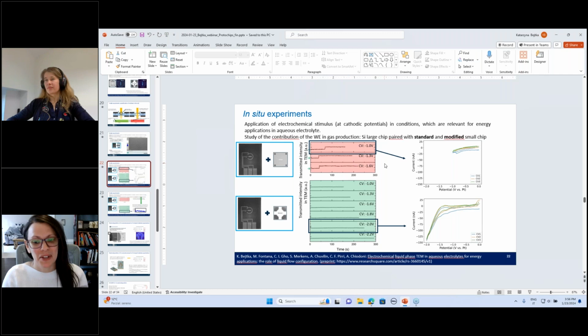And so you touched on something that there was another question about too. The question was, is it more difficult now with the modified chips to intentionally generate a bubble and de-wet the cell if you want to do higher resolution or diffraction or something like that? So with this modified cell, we actually need to go to quite negative potentials. And another thing that we can do is stop the flow, and then the cell saturates with the gas more easily because we are not removing the products of the reactions. So I think this answers the question. Yes, it is more difficult in the sense that we need to go to more extreme conditions. So it's not as easy as it was before. Before it was too easy.